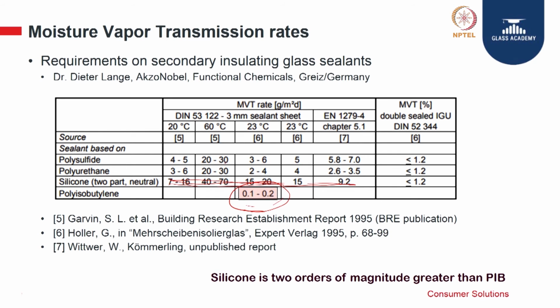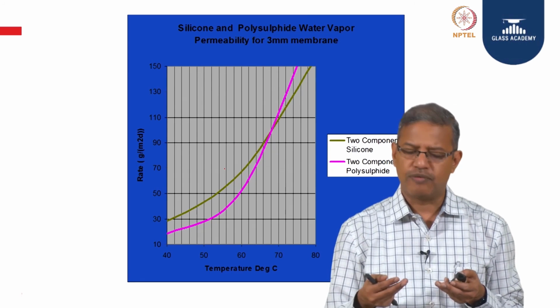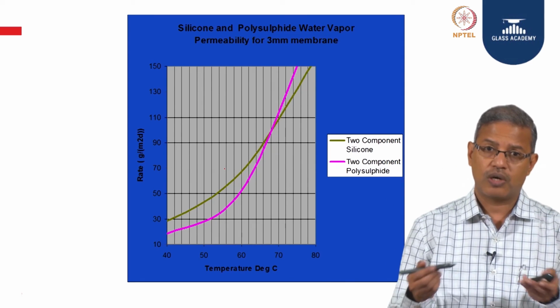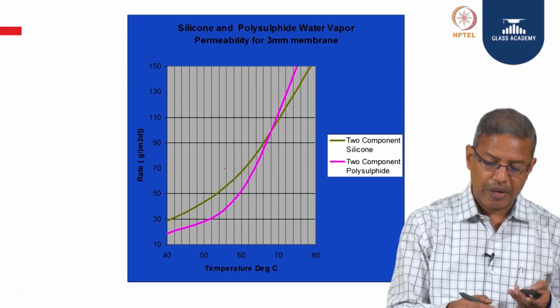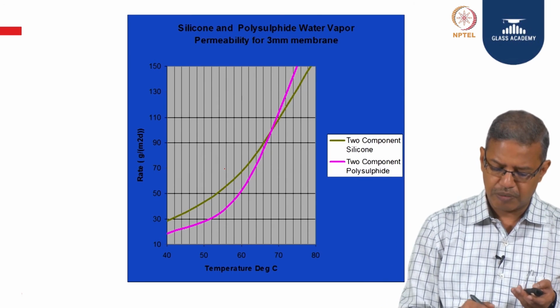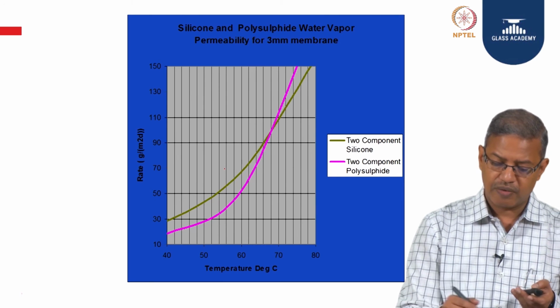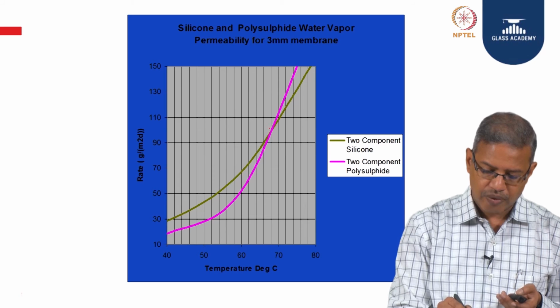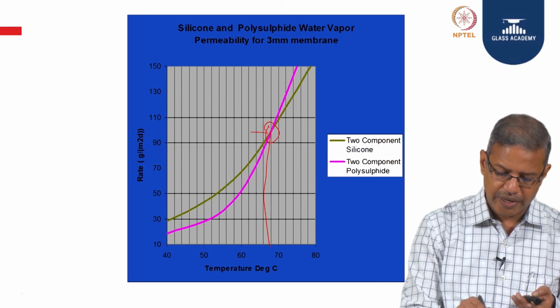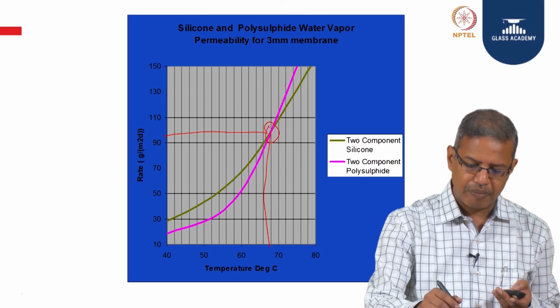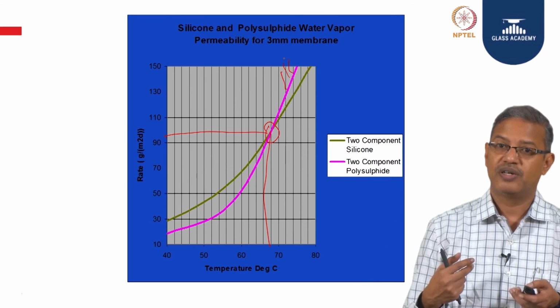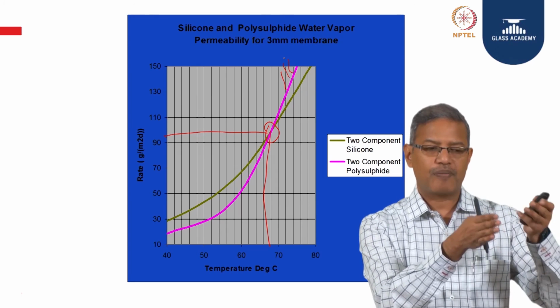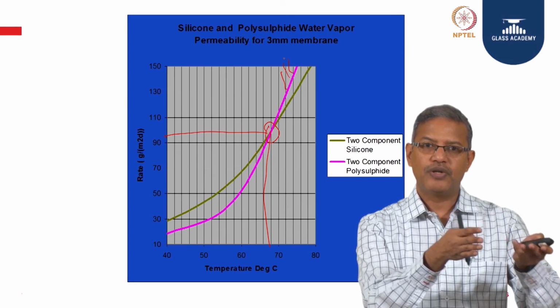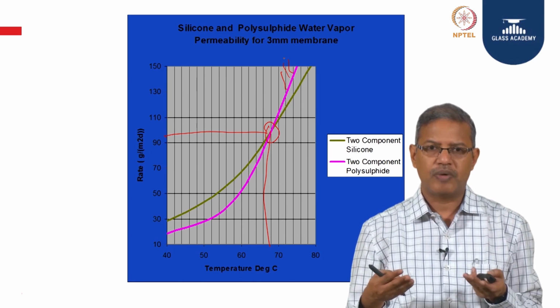Individually you may have some organic sealants which are good in moisture vapor transmission rates, but when it boils down to a combined unit, if you see this slide, the values we saw earlier were in multiples. But when you make a DGU, subject to a 3 millimeter membrane and to temperatures, you can see here that at this temperature the polysulfide has already beaten silicone and started absorbing more moisture. Individually you may have a product or chemistry which is good, but what happens to the long term performance when you make it as a DGU and subject it to temperature?